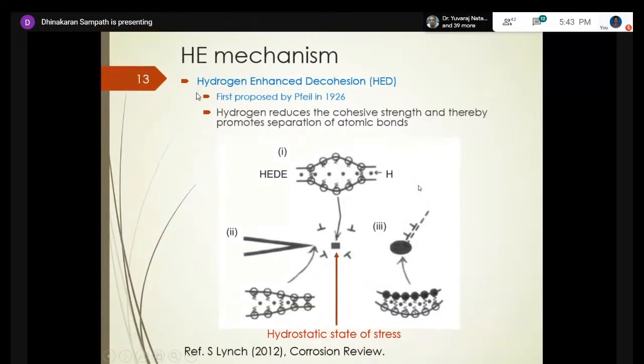So we are going to look at some models that explain the mechanism. This is a very early model, hydrogen enhanced decohesion. What happens is, in the presence of hydrogen, it lowers the cohesive strength of the atomic bonds. So it just unzips and initiates a crack, which is atomic lattice distance sharp. That means it will have a very high stress intensity at this location, and it just unzips all along. That is why they call it decohesion. It just separates.